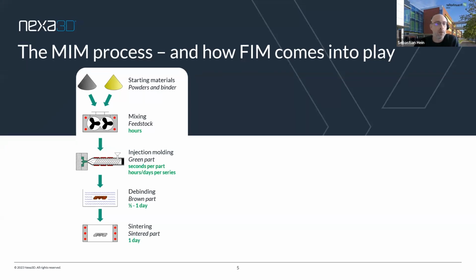it further placed into a furnace, where the rest of the binder is thermally decomposed, and then you usually go directly to the sintering temperature, and you consolidate your part by basically fusing together the powder particles. While this is done, they shrink and eliminate any porosity, so that you receive a shrunken version of this injected part, but usually with a density of around 95 to 100%, depending on the material.